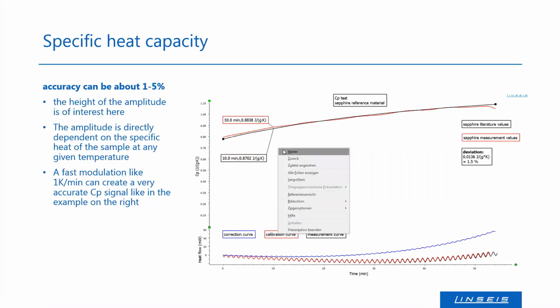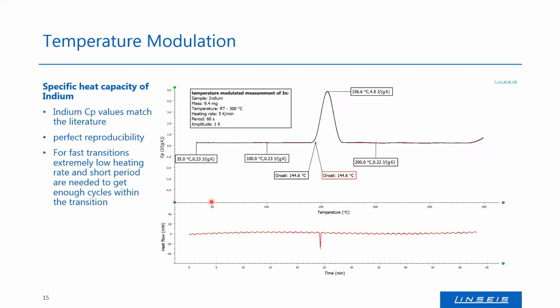Now, sapphire is inert. So let's talk about something other than our calibration standard. This is why I've measured indium. Just to be sure, this is basically the same calibration. We calibrated with sapphire, with roughly 0.7 joule per gram Kelvin at room temperature. And I also measured indium here. What you can see here is the result is 0.23, and the literature says it's 0.233.